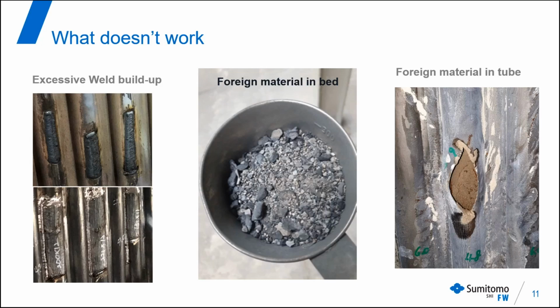One good example here is that there has been a tube leakage, and after that there is a lot of bed material in the tube. If this is not cleaned up, it will cause rupture of the tube, as it has happened here. You can see from the form of the rupture that there has been a short-term overheating due to the material from the earlier leakage in the tube.